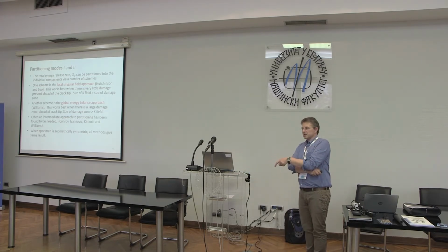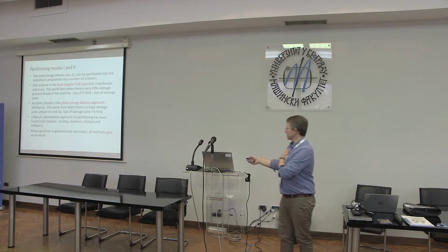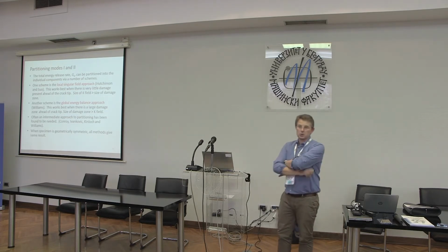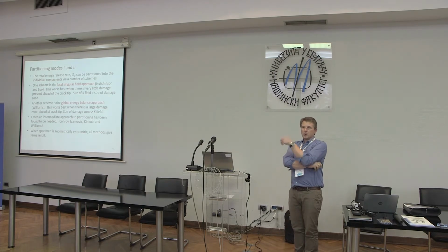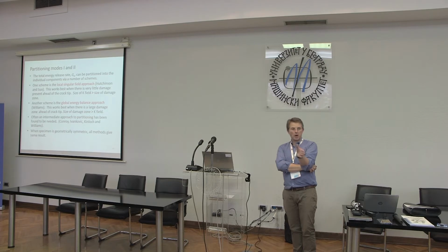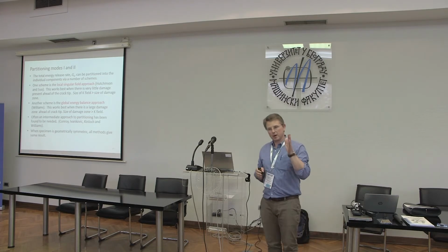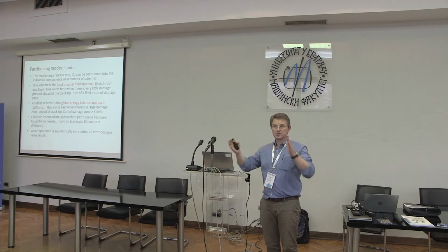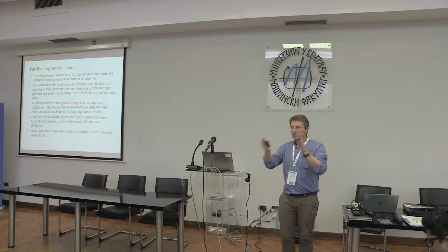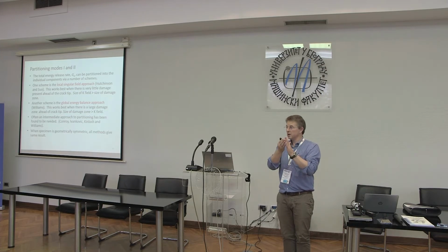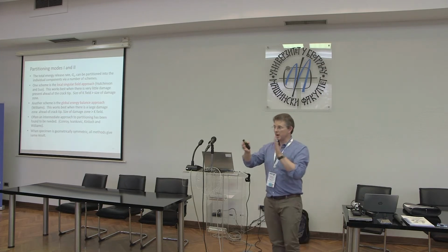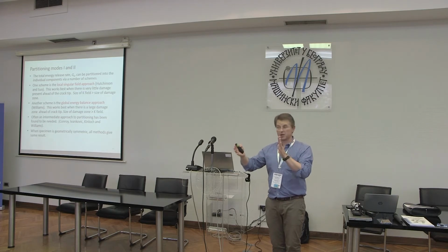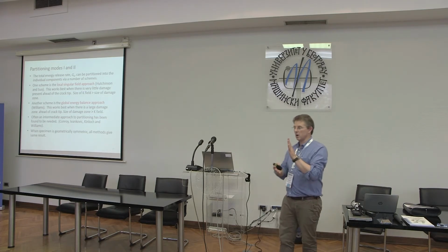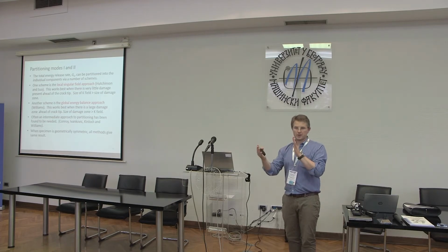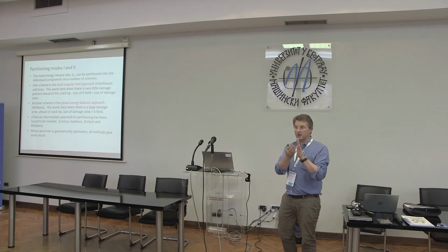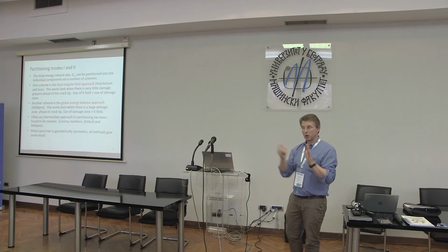So a pragmatic solution was actually put forward by these guys who said, well, actually, what we're going to use is we'll have some way of working out where we are between these two limits. If we imagine the local singular field approach and the global approach as extremes in our fracture process, we're somewhere in between in a real material. If we can devise a scheme for working out where we are, and they did this based upon cohesive zones, then you can work out your factor of singularity, which can range from 1 if you're completely singular to 0 if you're completely global.